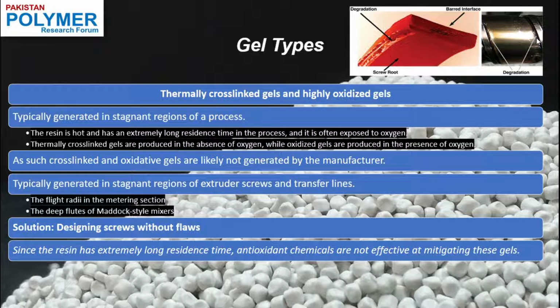These types of gels are explicitly related to the screw type and the design of the extruder. So the only method to reduce these types of flaws is properly designed screws. Even if you use antioxidants, you cannot use them for a longer period of time, because these gels are created when the resin has to stay for such a large period of time that even these antioxidants don't work enough, and this will actually increase the cost of your overall product.